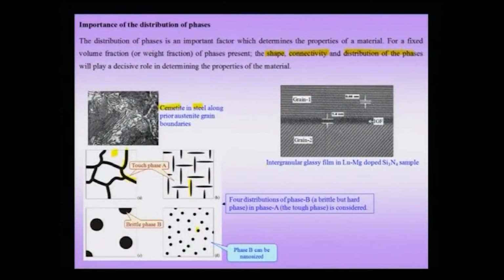Now, another example, for instance, this is the right hand example. This is the example of an intergranular glassy film in a silicon nitride sample. This happens to be a lutetium magnesium doped silicon nitride sample, and you are noting that there are these crystalline regions on the top and bottom, labeled as grain 1 and grain 2, but there is an amorphous region along the grain boundary, which is very similar to the continuous network of the brittle cementite along the prior austenite grain boundaries.